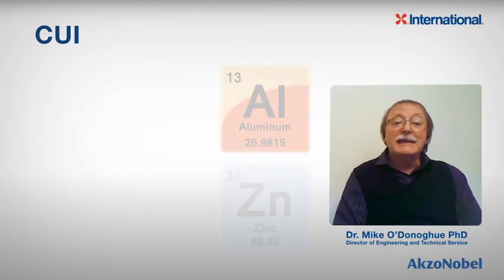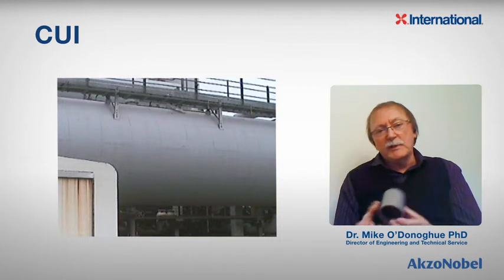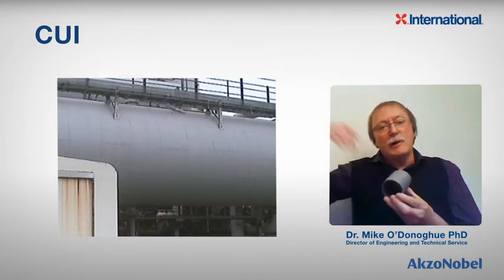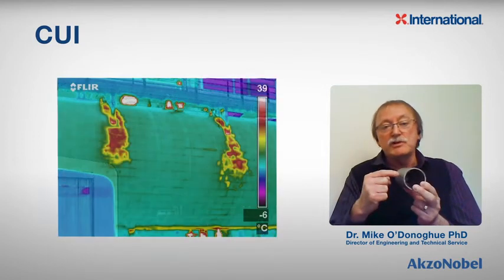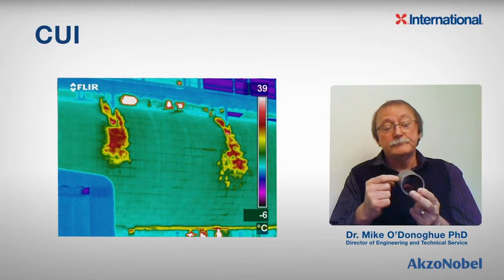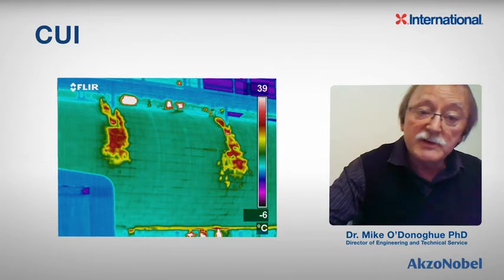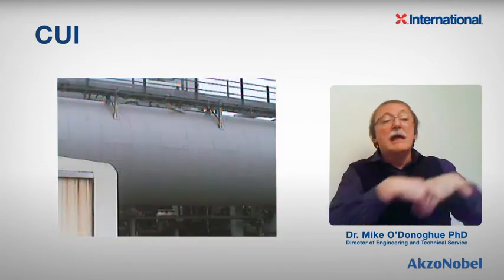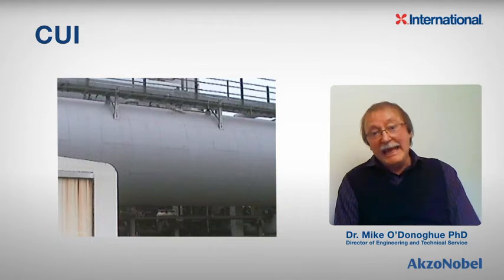And then the aluminum is not particularly effective. It's consumed. And so we are thinking to ourselves, I don't have much water in here, do I? It's not like a swimming pool on top of it. I've just got a tiny little bit of moisture in there. What's the problem? I'm heating it up. The oxygen's coming out. It's boiling out. No. The oxygen that's in there has a very short diffusion path down to this steel, and corrosion can happen very easily. So thermal spray aluminum, for all its technical prowess on the atmospheric side of the equation, where it's unequivocally brilliant, has problems here.